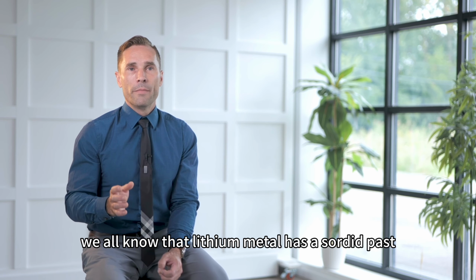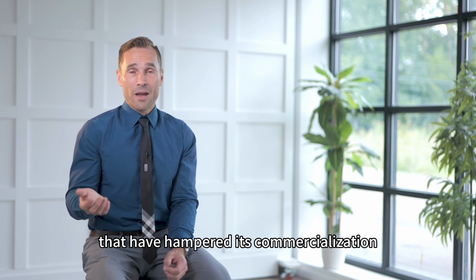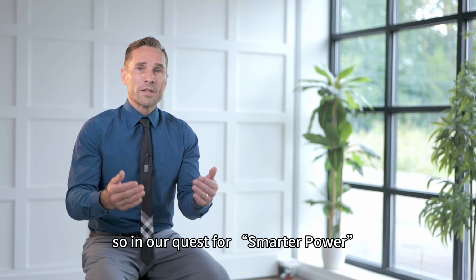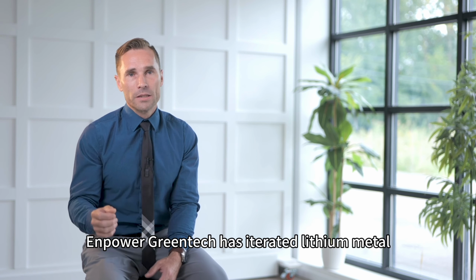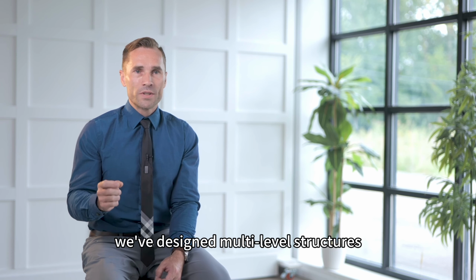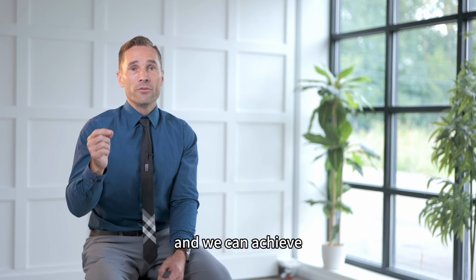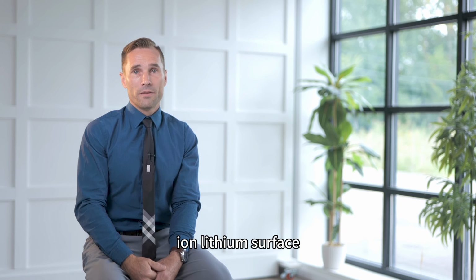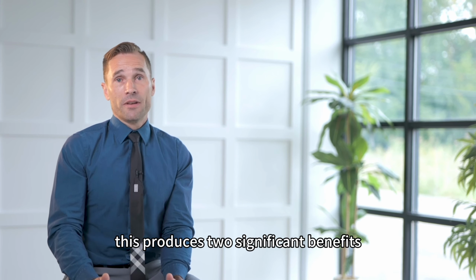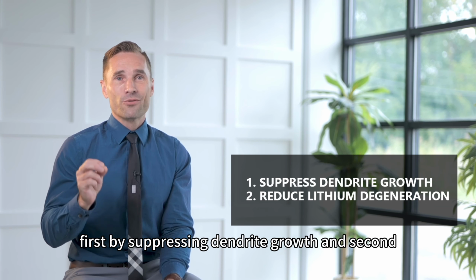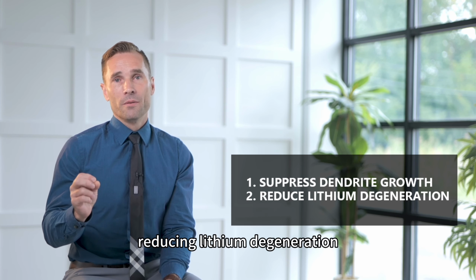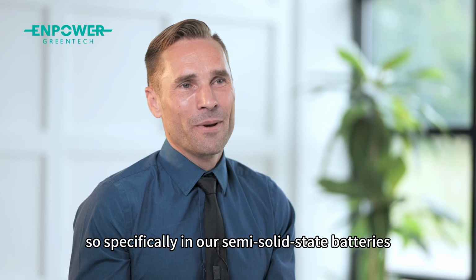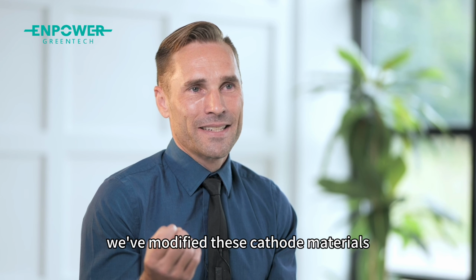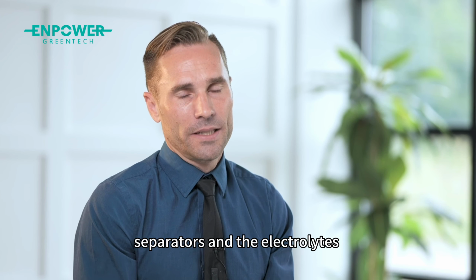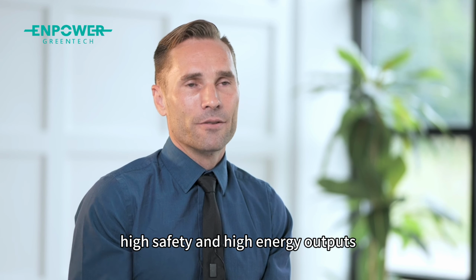However, we all know that lithium metal has a sordid past with myriad issues that have hampered its commercialization. So in our quest for smarter power, Enpower Greentech has iterated lithium metal protective layers, and we've designed multi-level structures so we can achieve uniform potential on the conductive ion lithium surface. This produces two significant benefits: first, suppressing dendrite growth, and second, reducing lithium degeneration. Specifically, in our semi-solid state batteries, we've modified the cathode materials, separators, and electrolytes to fit various application scenarios, while always ensuring high safety and high energy outputs.